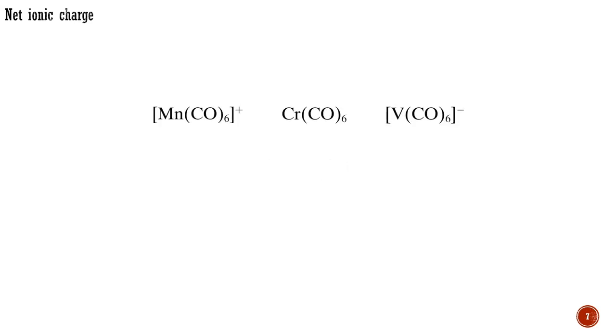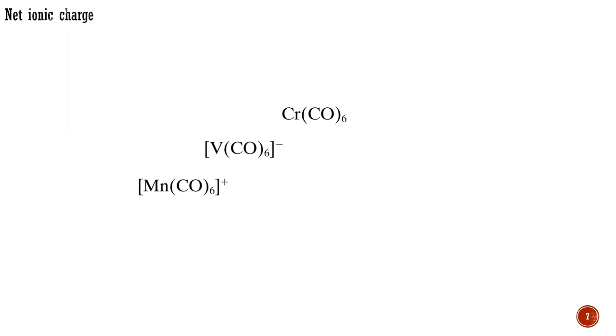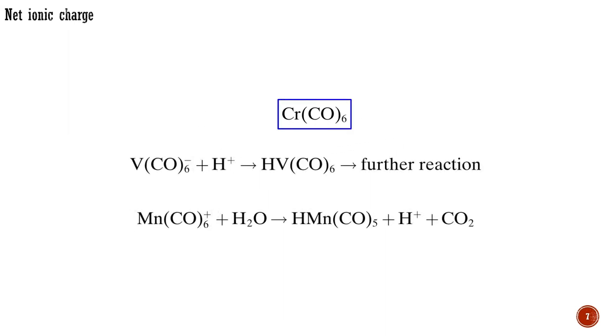An increase in the positive ionic charge of a complex with this general formula decreases any backbonding to the ligands, all else being equal. It also makes the complex harder to oxidize but easier to reduce and changes the reactivity toward nucleophiles and electrophiles. For example, the carbonyl complexes shown here are isoelectronic, but only the negatively charged complex reacts readily with electrophilic proton, and only the cation reacts readily with nucleophilic molecules like water, while neutral chromium hexacarbonyl does not react with any of these reagents.